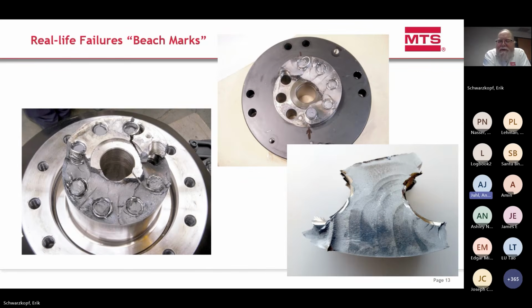Sometimes you see beach marks on these fracture surfaces, and these beach marks indicate where the load changed, or where the stress intensity or stress amplitude changed. In the lower right-hand curve, you can see a few beach marks on this broken part.